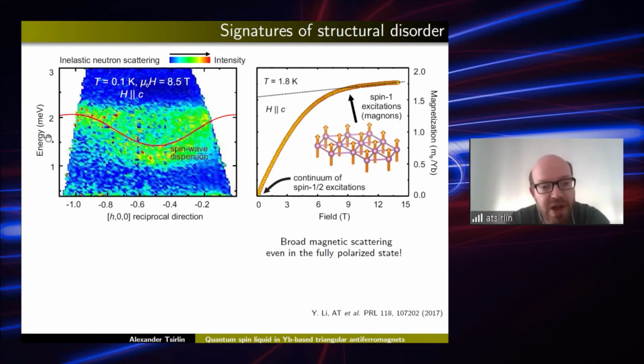Then we go and measure them with inelastic neutron scattering. And surprisingly, we don't see anything that really looks like spin wave dispersion. Well, basically, we see still a very large blob of intensity. You can try to put some spin wave dispersion in here, but that pretty much is not the normal spin wave. All right, so for some reason, even at the fully polarized state, which should be ferromagnetically ordered, we still see a very broad dispersion.